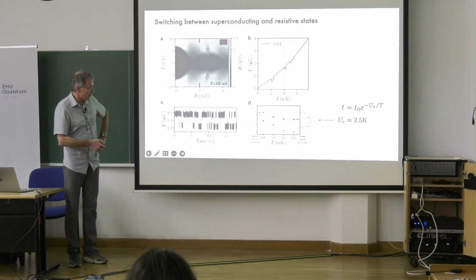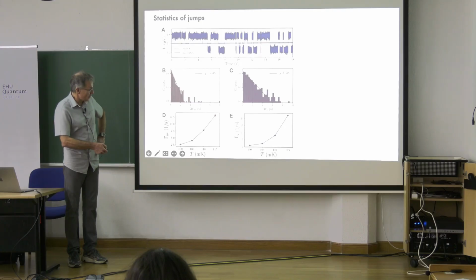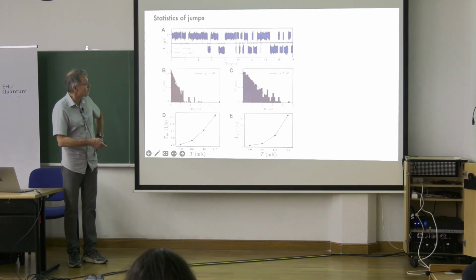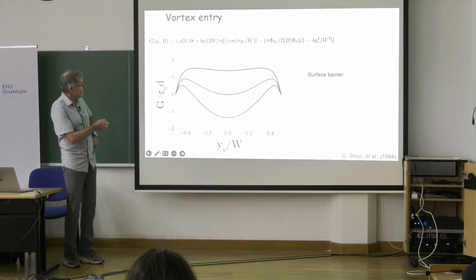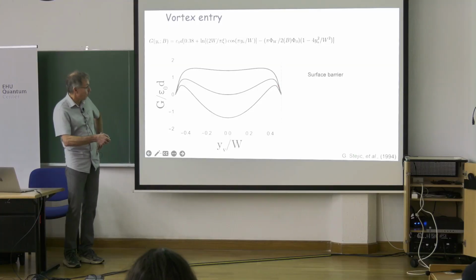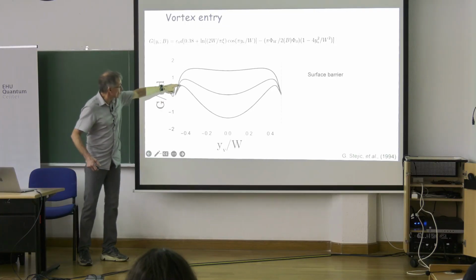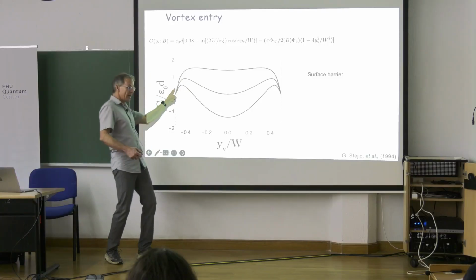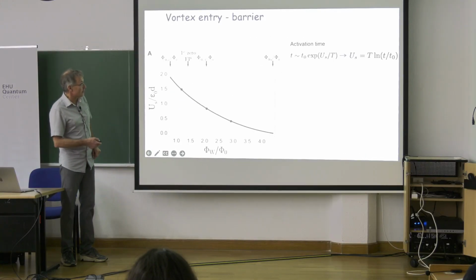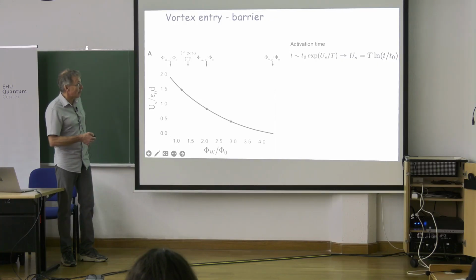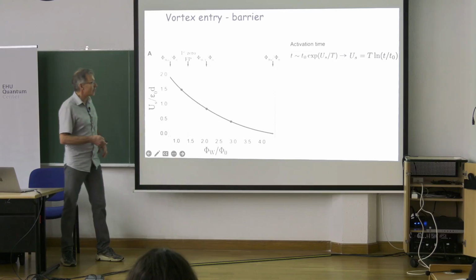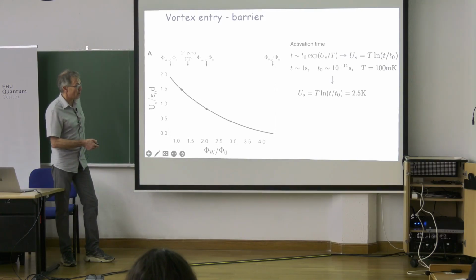This is the switching. The switching time depends exponentially on temperature. So that fits an exponential behavior. From here, we can extract the barrier. Or here, it's the time that goes up exponentially, not the rate. Then one can calculate the potential for a vortex as a function of coordinate for different fields. And there is a barrier which a vortex should overcome for going in, and this will be the barrier for going out. So this barrier can be extracted simply by fitting the time of the event, and from this we get that it is about 2 Kelvin.